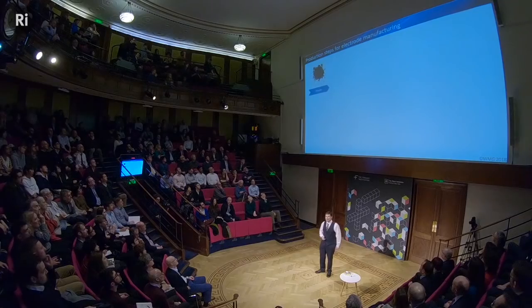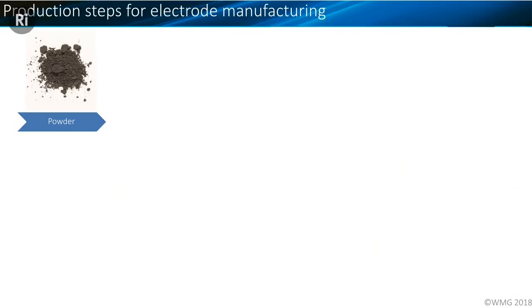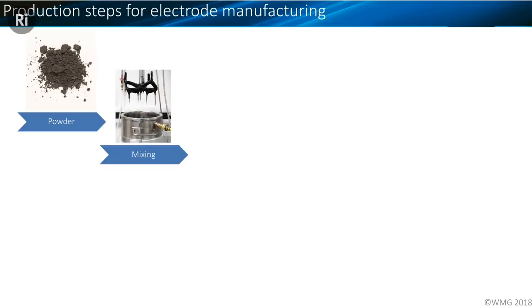So what we do first is we take our powder and we mix it into an ink. We mix it with carbon black typically, which is a nice conductive additive that links the electrical current all the way from the particle to the foil. And we'll mix in some binders, and that's basically an adhesive that makes the carbon stick to the foil. And then we use a solvent which makes it liquid so that we can start to print it, and we're going to dry off that solvent. And as we dry the solvent off, it's going to leave porosity behind it, and that gives us that beautiful microstructure that you saw earlier.